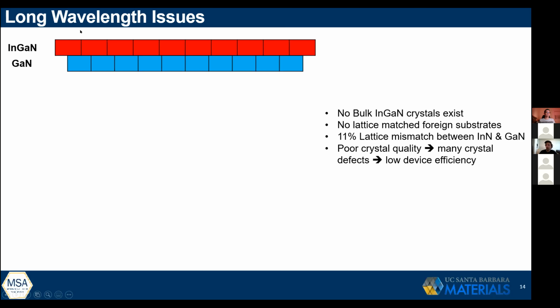To get to a longer wavelength, you remember that plot where we could span the entire UV to infrared with nitrides. The infrared portion was indium nitride, and the intermediate stage was GaN. There are no bulk InGaN crystals, and so to form a red nitride-based LED, you have to have some indium gallium nitride grown on top of GaN. However, there's an 11% lattice mismatch between indium nitride and gallium nitride, and so this mismatch leads to poor crystal quality, which leads to defects and poor device efficiency in general.